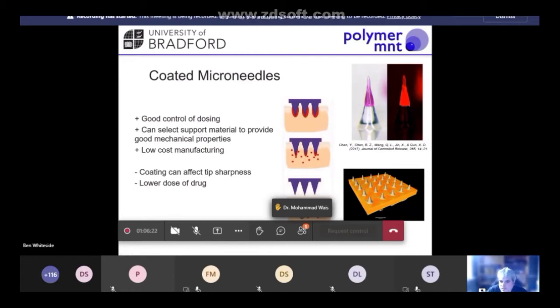But one of the main limitations with the coating techniques is when you consider the amount of drug that you can apply onto an array. It's only forming a small volume on the tip of the needle here. So sometimes for drugs that need quite a high payload to be effective, that can be an issue in that you need quite large, dense microneedle arrays in order to administer the amount of drug that is required.